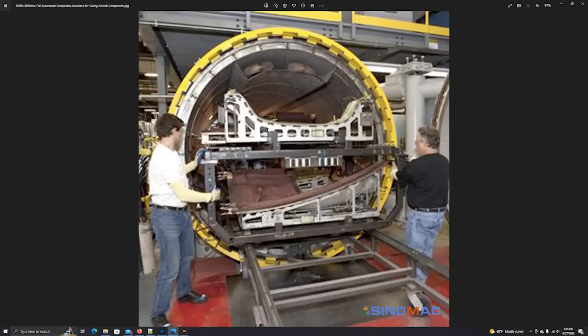They used vacuum bagging. So compare the difference in fabric compaction. They used 14.7 psi as opposed to 40 to 100 psi. So you're not getting as tight of a compaction as you are by using an autoclave. So there, right there, is a discrepancy. They did not use an autoclave, so therefore their compaction wasn't as good, let's say, as the aerospace industry who